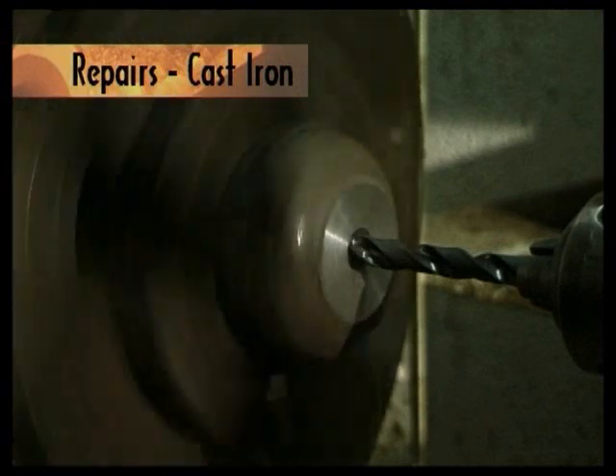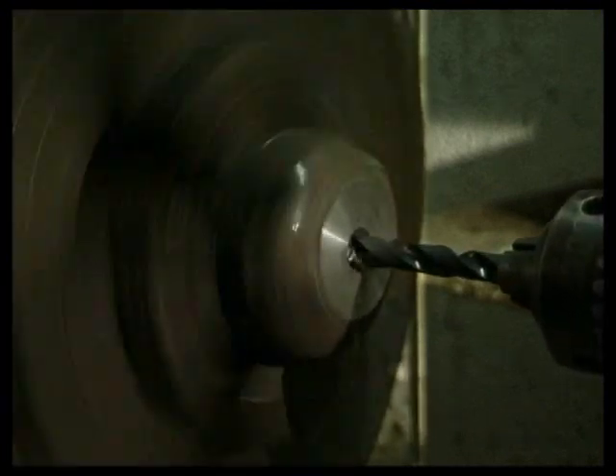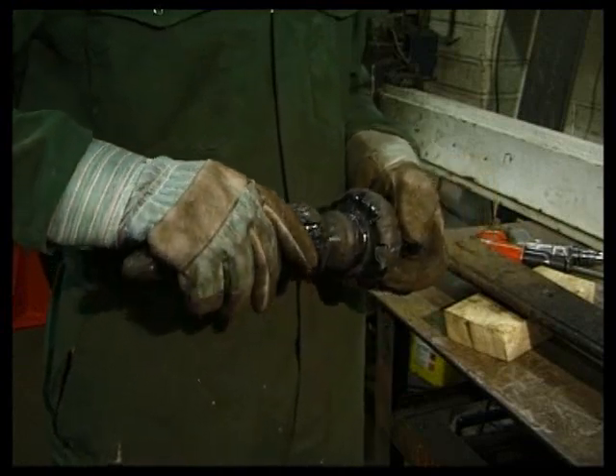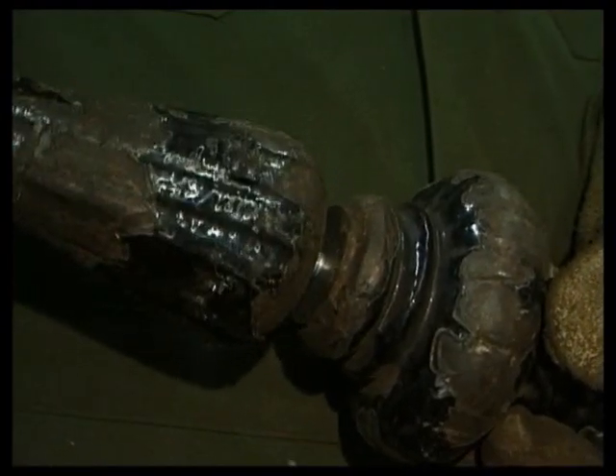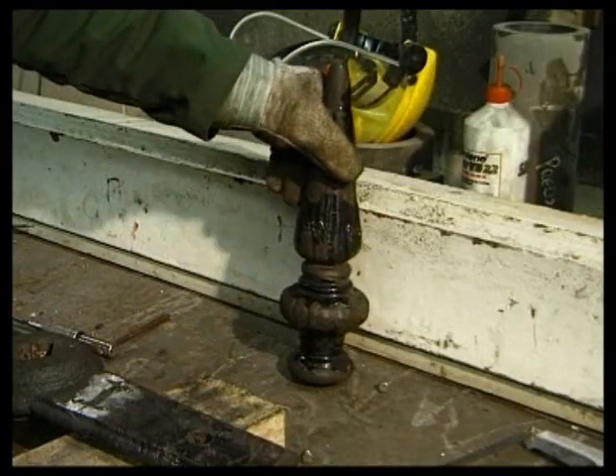Cast iron, being brittle, should always be repaired by cold processes if possible. It may be feasible to drill broken components and thread the holes. They can then be screwed back together on studding, bedded on a suitable mastic to keep out water. Remedial work should generally be completed before painting so that the paint coat subsequently seals the repairs.